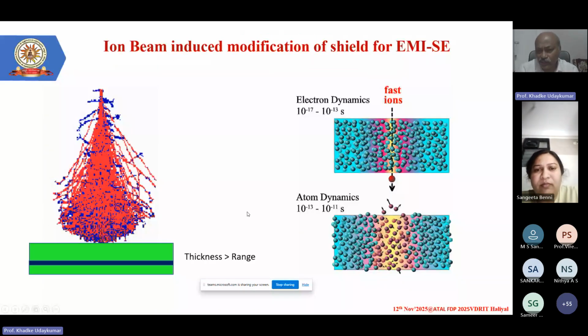The mechanism I don't have to repeat once again. When the fast ions are going, you can see that it is creating a thermal spike model, and it will be creating porosity in it. And the pore size is not equivalent throughout the medium. So at the entry level, the pore size will be smaller. At the exit level, the pore size will be larger. So it creates a cone kind of shape. So these cone-shaped pores are very, very favorable for our experimental results.